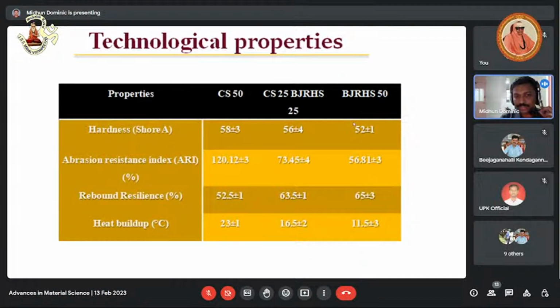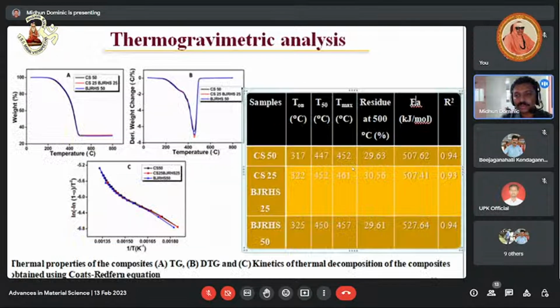So the same trend is also observed in the case of hardness, heat buildup, and abrasion. Look at the abrasion resistance index value. If you make use of commercial silica, it has a 120 abrasion resistance index, but it is only 56 for BJRHS.